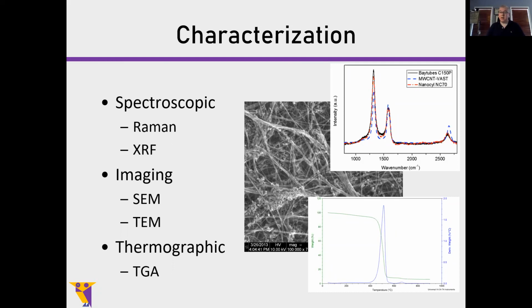Imaging gives you an idea about the network, about how big the tubes are when they're multi-walled, and other things like that. But thermogravimetric analysis is very handy. Why? Because it's extremely easy to run. This is basically an analytical balance inside of an oven, and you heat the oven and you watch the mass loss. So it's extremely easy to run. You get nice curves like you see there. There's the mass loss curve in green and the derivative or rate change.